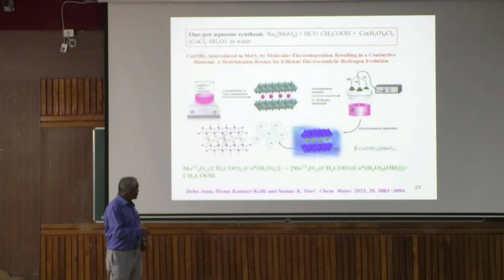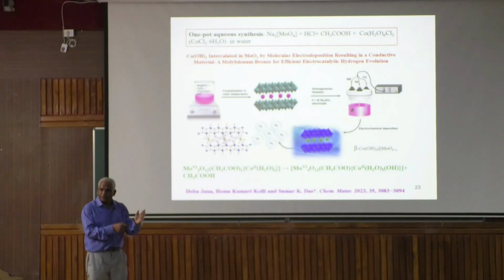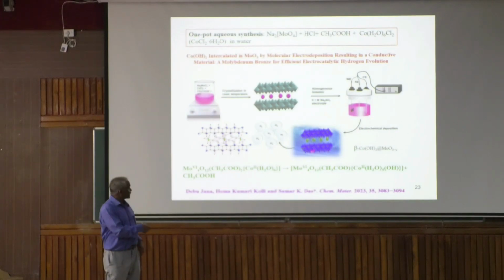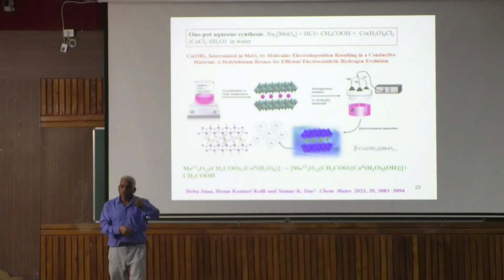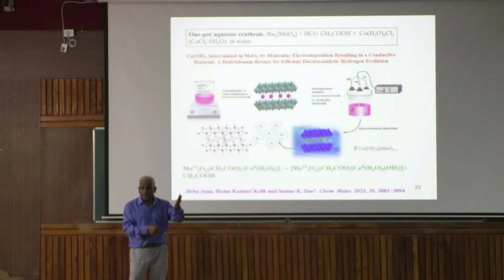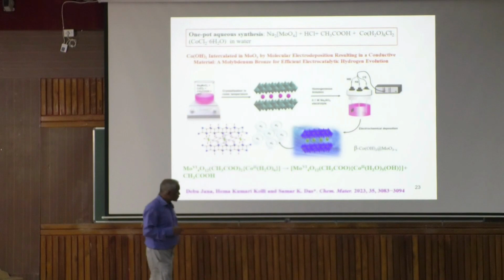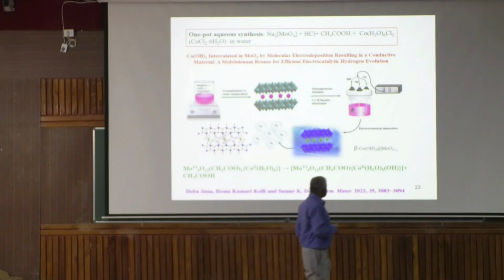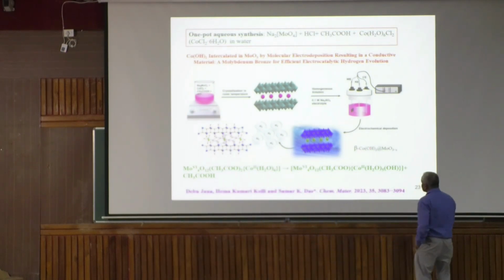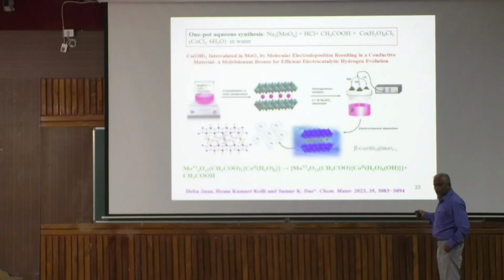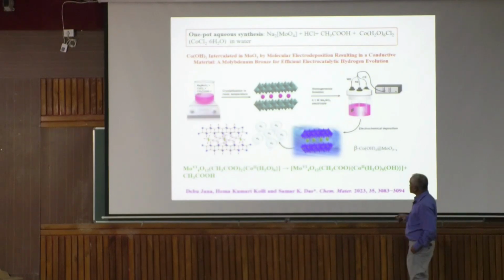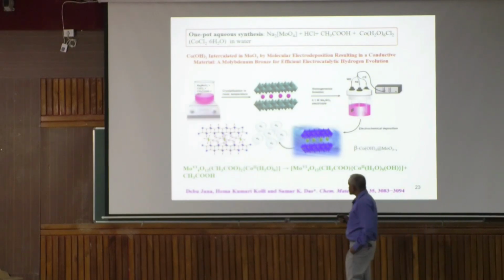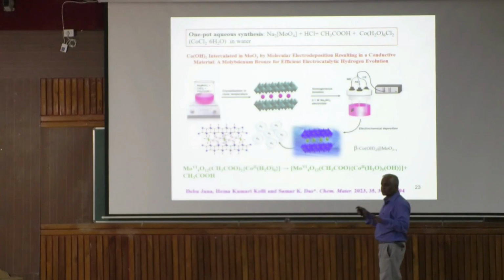You may ask me, maybe if it is the beta form, it will come out as a physical mixture, the beta hydroxide and MoO3 side by side. It is intercalated. We check by PXRD because the 2 theta angle will shift to the lower side if it is intercalated. So that way, we prove even in the acidic medium, you can generate beta cobalt hydroxide intercalated. It is also a molybdenum bronze now because some of the Mo is in the reduced state, and it has a very shiny, lustrous color. In the continuous hydrogen evolution, day and day, week and week, nothing happened.